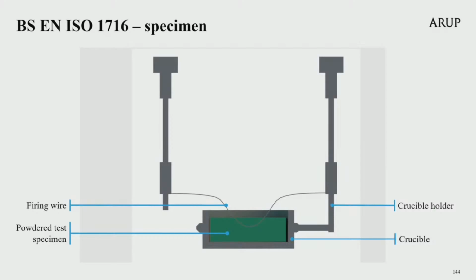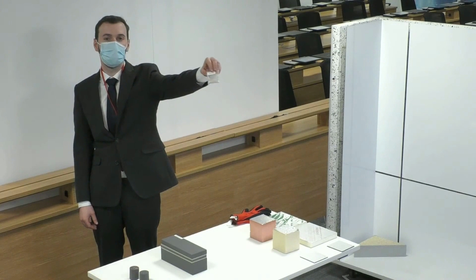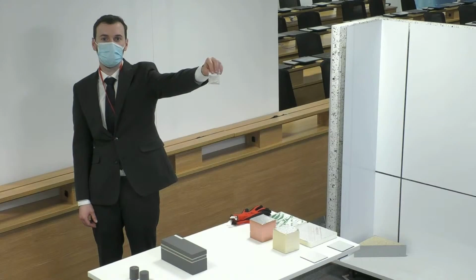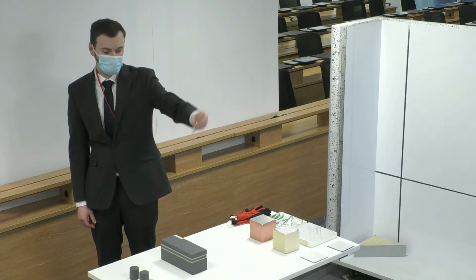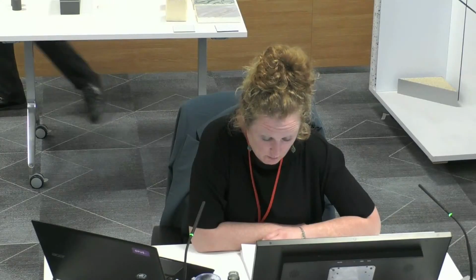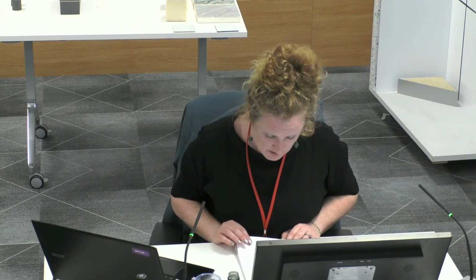50 grams of the specimen is taken and ground into a fine powder. Tom is now holding up a small bag of 50 grams of ground polyethylene. 0.5 grams of the specimen is placed in a crucible along with 0.5 grams of benzoic acid. This is to assist the sample to combust. This crucible is just a non-combustible holder that is used to store the material within the bomb.